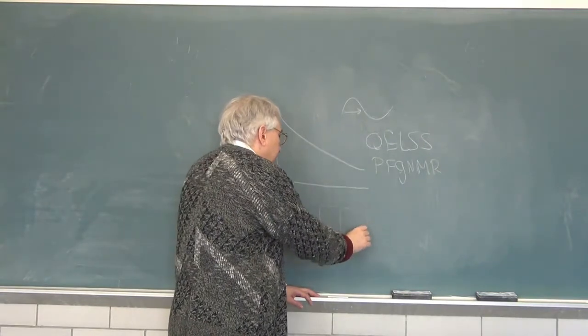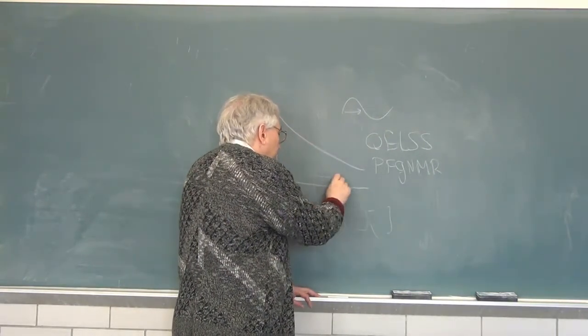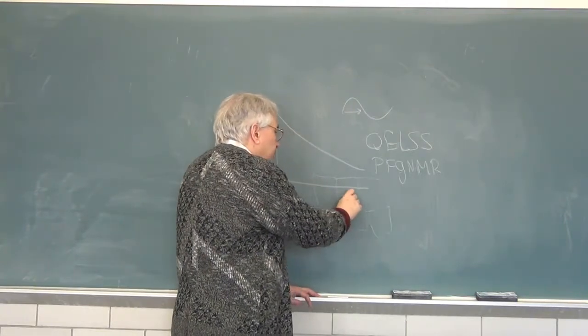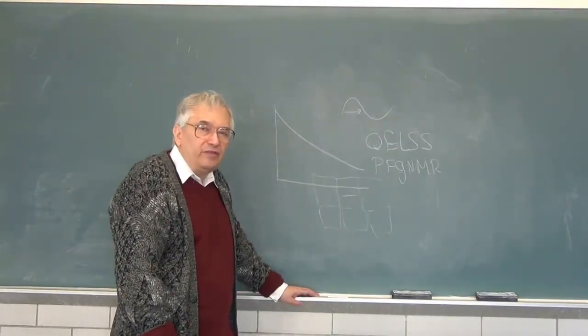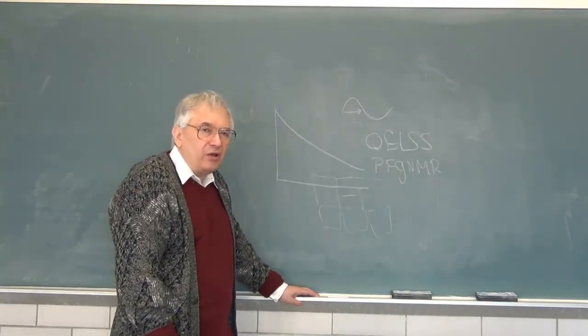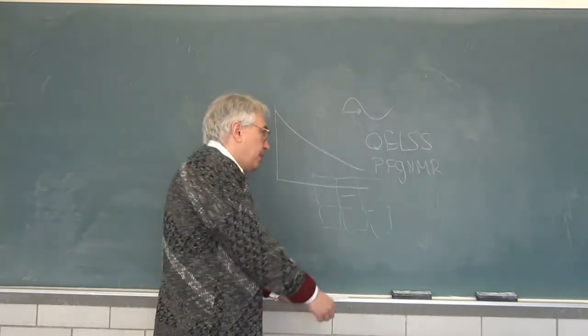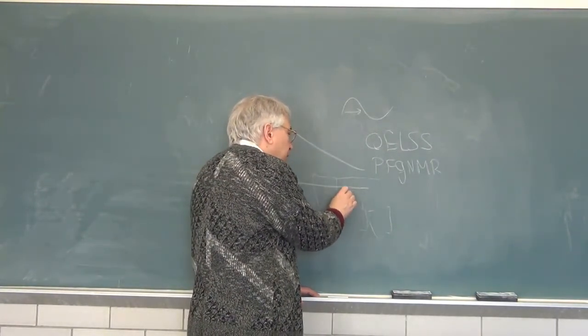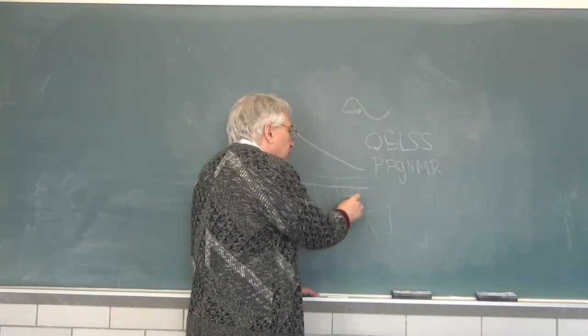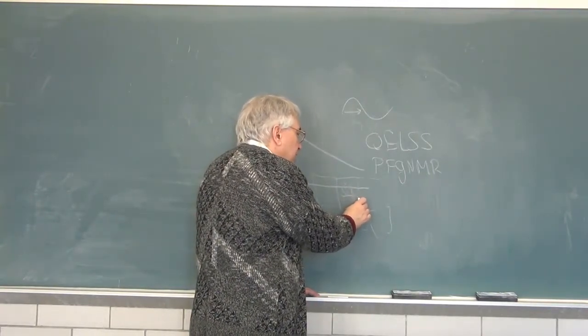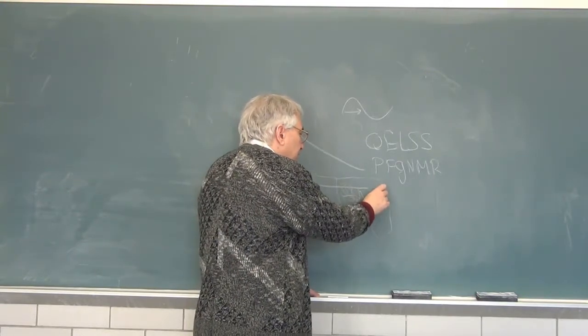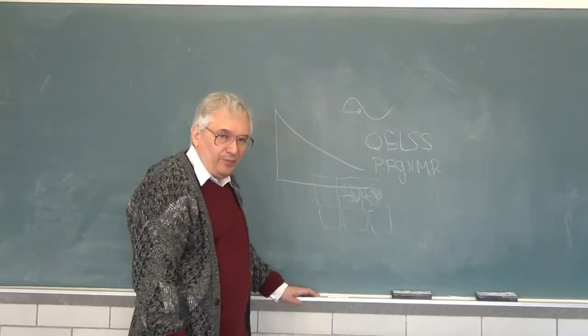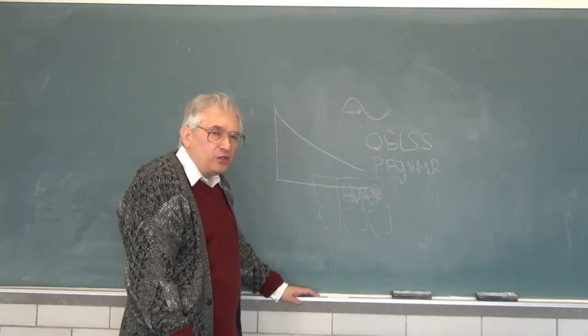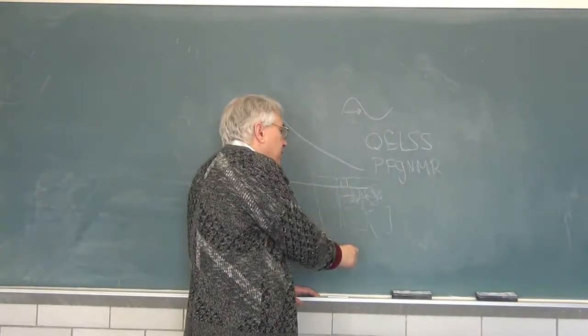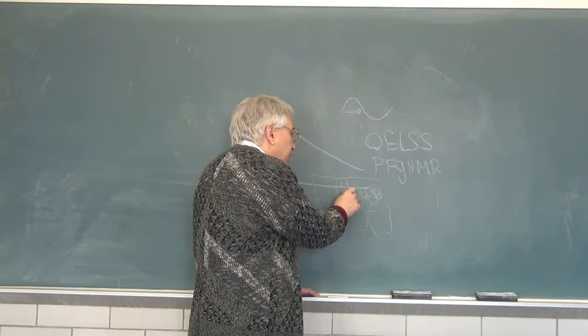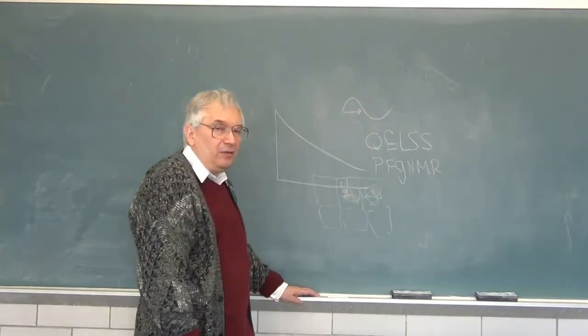Suppose you had a system in which you had boxes, and inside the potential energy of the diffusing particle was fairly flat, and then there were potential energy barriers that the particle had to climb. If you watch a single particle, it will do a random walk inside a box, but only rarely will it find enough kinetic energy to get over the potential energy wall and get into the next box into which it is now trapped. If you look on short distance scales like this, you mostly only see the particle jittering back and forth in the box, which it can do quite rapidly.